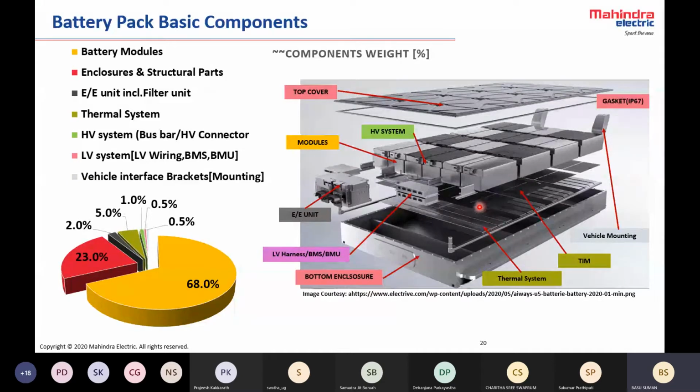So we put thermal interface materials which fill the gap and make sure the heat transfer path is provided. Thermal interface materials generally have a conductivity equivalent to water or a little bit more. So it is still about one order of magnitude better than air.